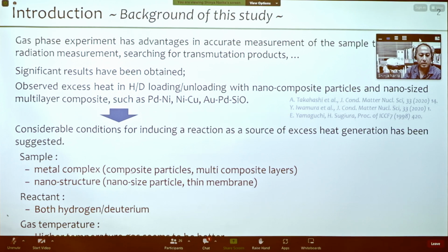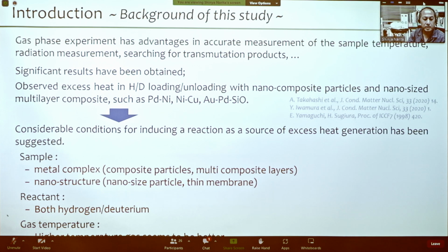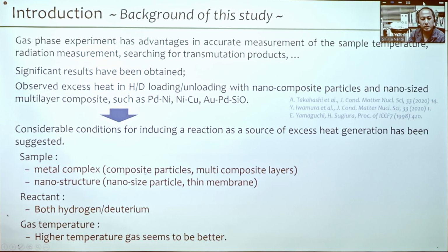So as for the sample composition and structure, the metal composites such as the composite particles and multi-composite layers seem to be some important key to induce a reaction. Also, the nanostructure such as nano-sized particle and the thin membrane seems to be effective for the reaction. And for reactant, both hydrogen and deuterium are effective. And concerning the gas temperature, high temperature gas seems to be the better. It is suggested.